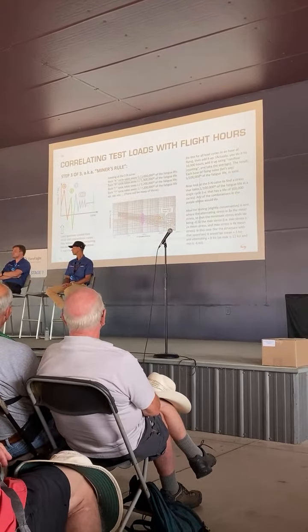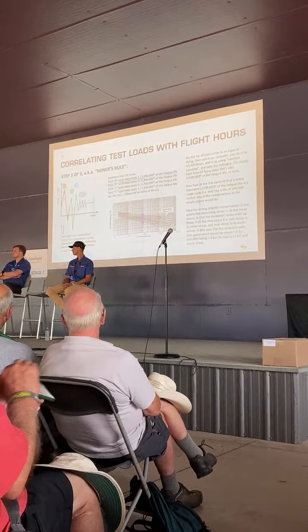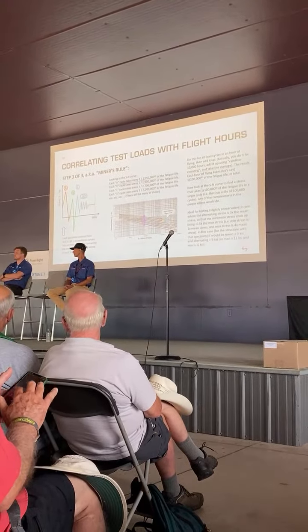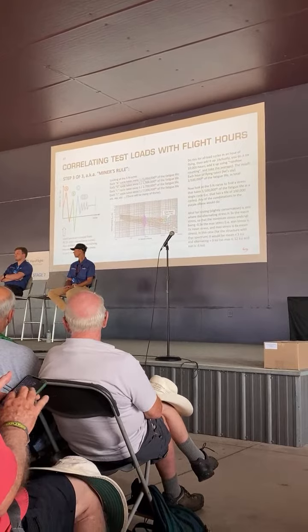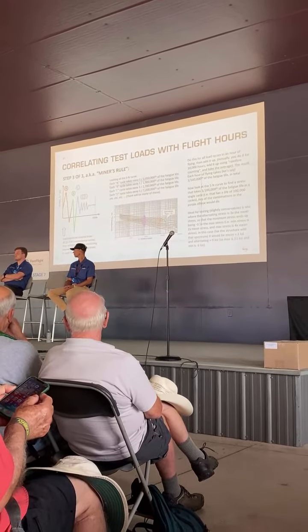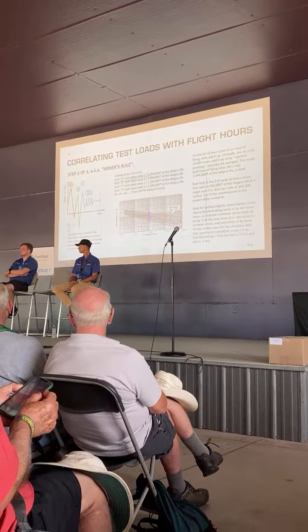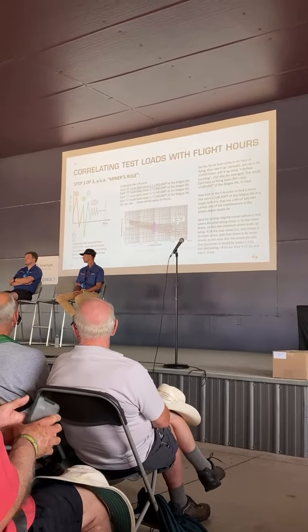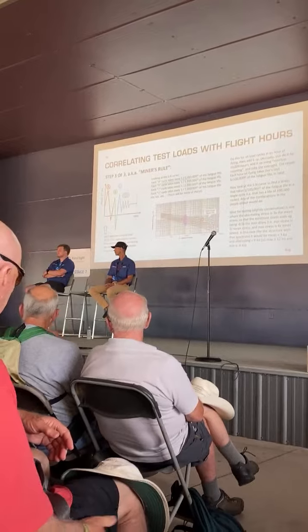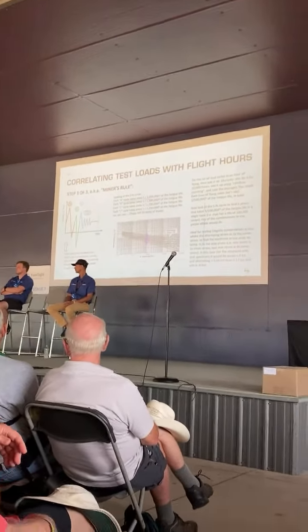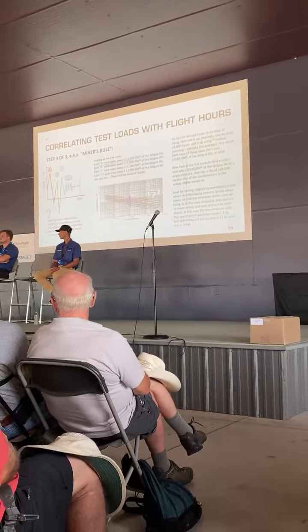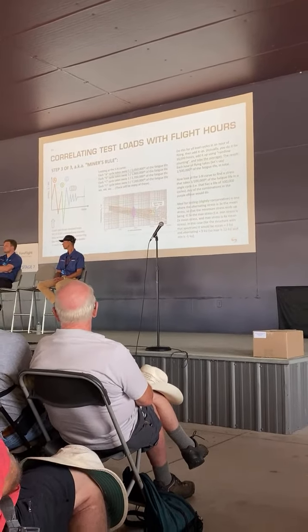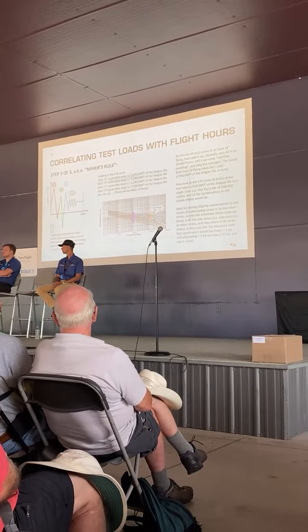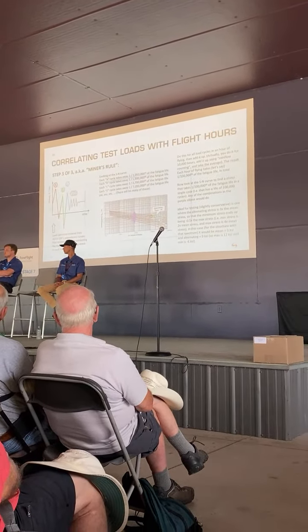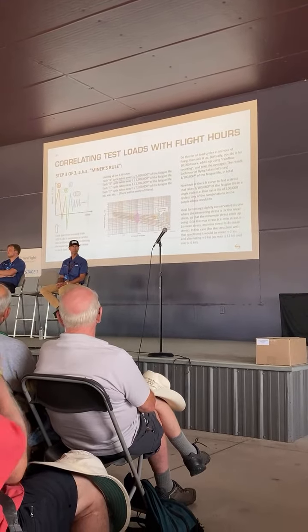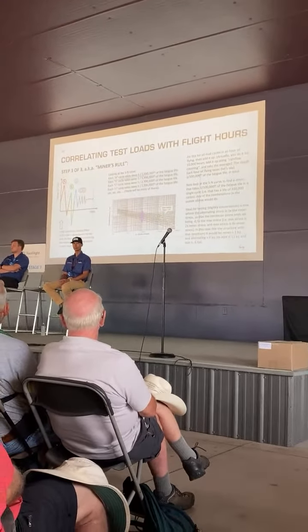And in effect, this is telling you that if you load a coupon, where we're loading these coupons, we take them, and I'll show this in the next slide, to limit load, or as much as they can take. We'll back it off just slightly, and we find the stress level of the life at that point. But these rivets are at a much lower loading. So Miner's rule is the way that you can take the amount of life that you measured at this high stress level and translate it into, okay, I have a finite element analysis model, I have rivet locations, and how long will the life be at all those locations?